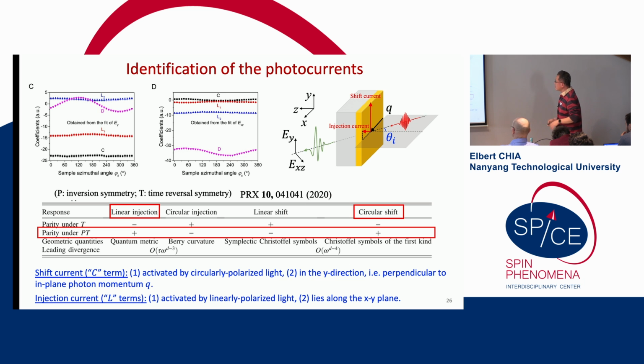Okay. So I don't have much left to say, but you can see that from a previous theoretical work by a Japanese group, they found that for samples symmetric under PT, the kind of photocurrent that's allowed is the linear injection current and the circular shift current. And so from our data, we can see that the Y component of the photocurrent consists of a shift part and the injection part, but the X component has only the injection part. And so the C term, which is the shift current, is activated by circularly polarized light, as we can see here, in the Y direction, but the injection current, which is the L term, is activated only by linearly polarized light and lies along the XY plane.